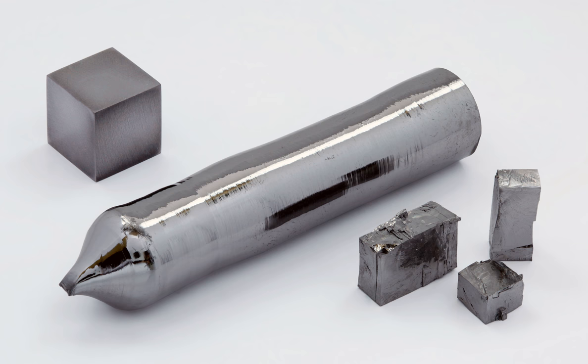For example, porous tantalum coatings are used in the construction of orthopedic implants due to tantalum's ability to form a direct bond to hard tissue. Tantalum is inert against most acids except hydrofluoric acid and hot sulfuric acid, and hot alkaline solutions also cause tantalum to corrode. This property makes it a useful metal for chemical reaction vessels and pipes for corrosive liquids. Heat exchanging coils for the steam heating of hydrochloric acid are made from tantalum.